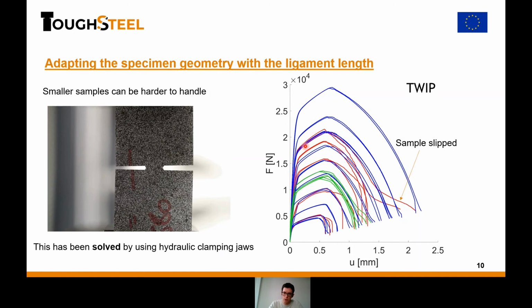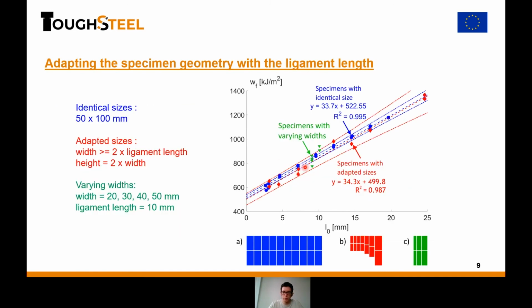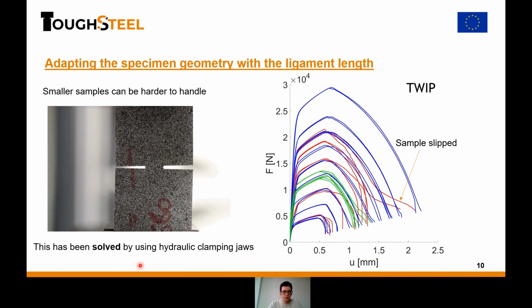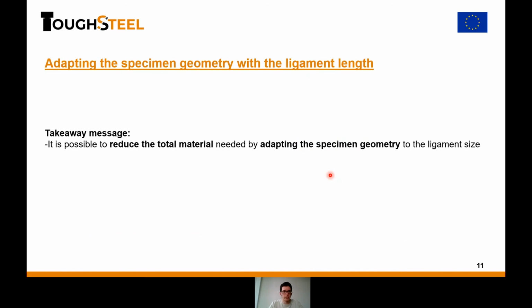You see that it fits quite well for the beginning of the curve until the maximum. And then when the cracks start to propagate, sometimes you see that it slipped and the curves are not identical anymore. This explains a part of why there's more spread of the values. But still, later this has been solved by changing the setup. We now use hydraulic clamping jaws, which is a lot better. But still, the takeaway message of this first part is that yes, it's possible to reduce the total amount of material needed just by adapting the specimen geometry.